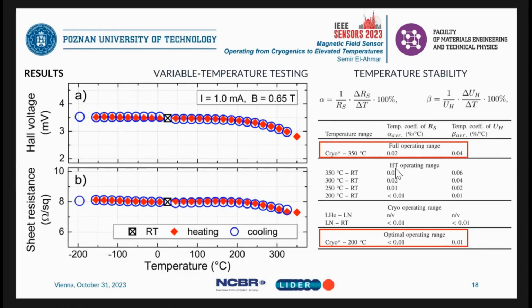However, if we make this range a little bit narrower, from cryo, which means here a liquid nitrogen temperature, up to 200 Celsius degrees, we can get these coefficients even below 0.01% per Celsius degree, which is extremely stable. And this could be the optimal range of operation for our sensor.